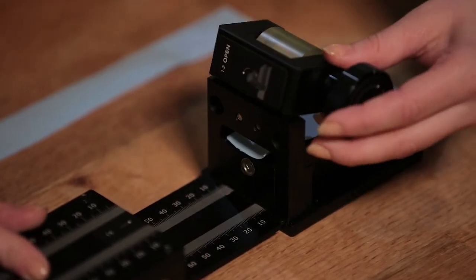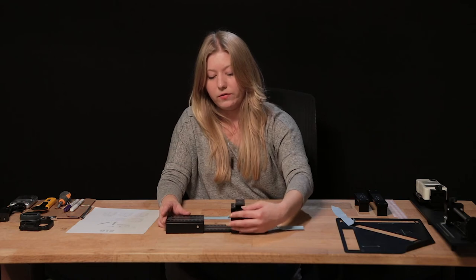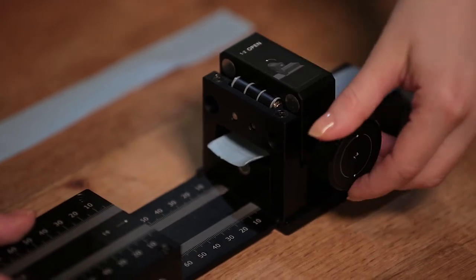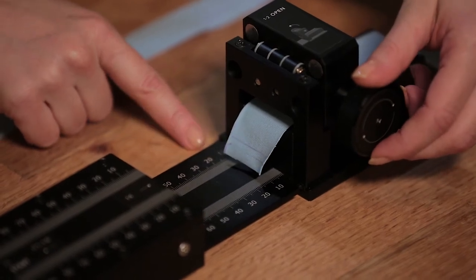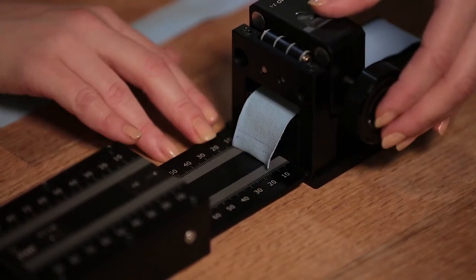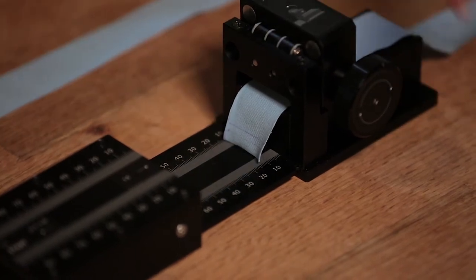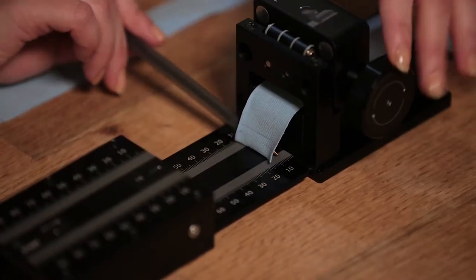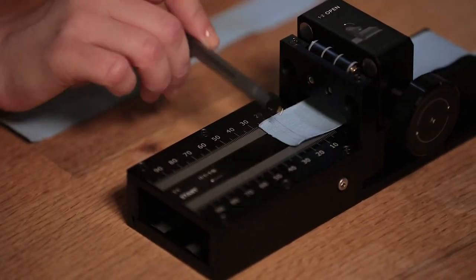There's a roller that helps you slide the fabric forward. Roll the fabric outward and record the number where it contacts the ruler. For me it hit 12 millimeters — that is your contact distance. Once it's hit the ruler, lift the little section of fabric up, push it back, and let it rest on the ruler to record your contact length. Mine is 27.